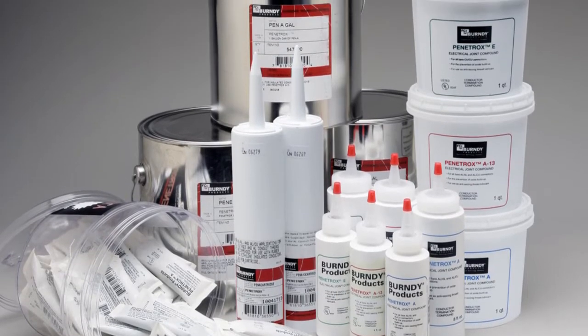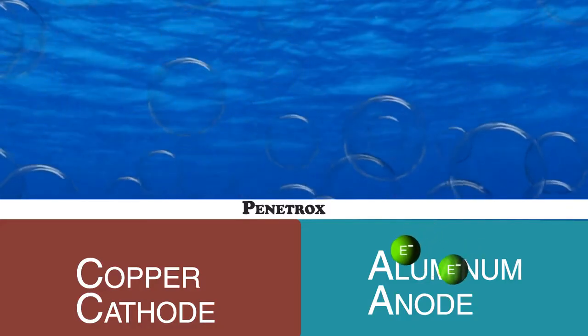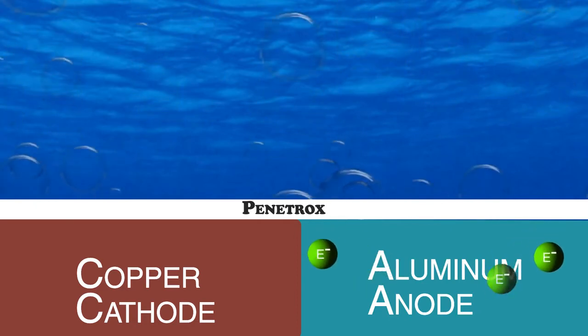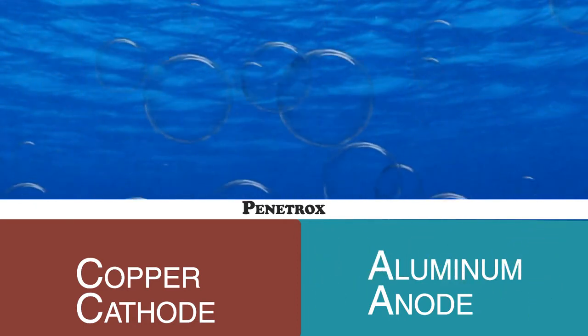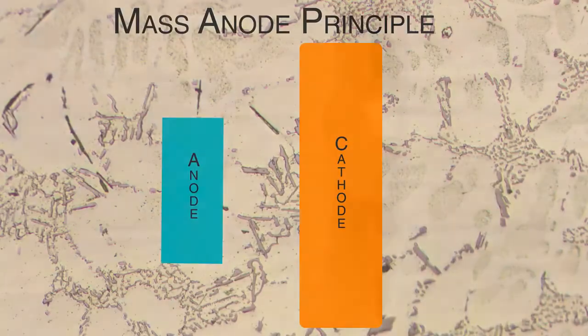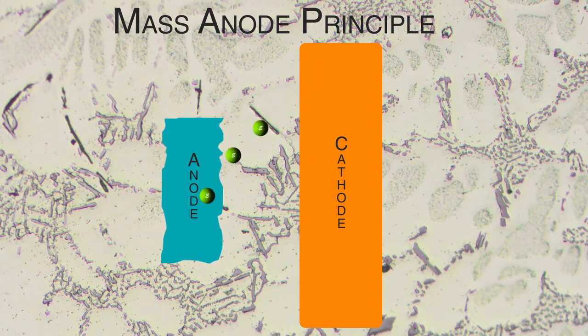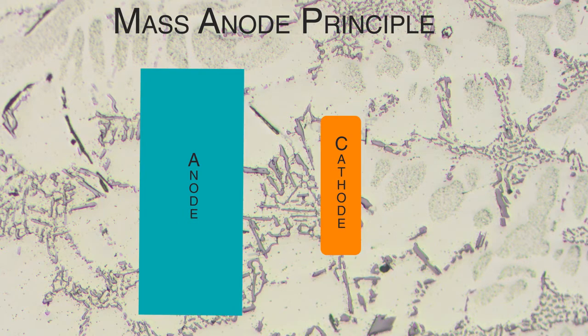If there's an abundant amount of oxide inhibitor, that prevents Mother Nature from getting into the connection or the electrolyte getting into the connection, that will reduce the galvanic corrosion. Another way of reducing galvanic cell is by plating the cathode, in this case, plating the copper. Another method of reducing a galvanic cell is to use insulation. And the last one that is often used, and this is why we recommend using aluminum for an aluminum to copper, is using a principle called the mass anode principle, where if your anode is significantly more massive than the cathode, the rate of corrosion is significantly reduced, so that it basically reduces the amount of corrosion over the life of the connection.